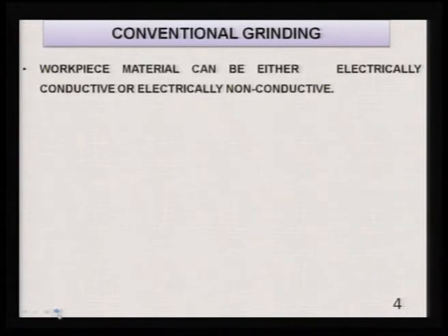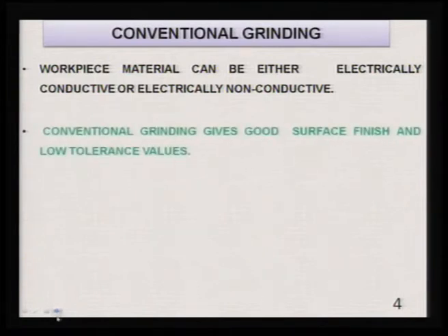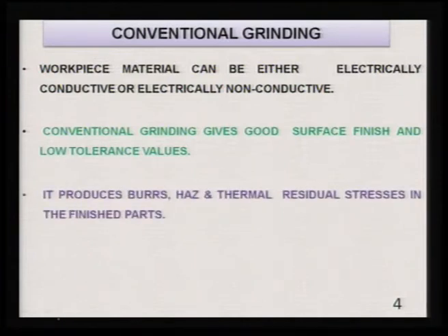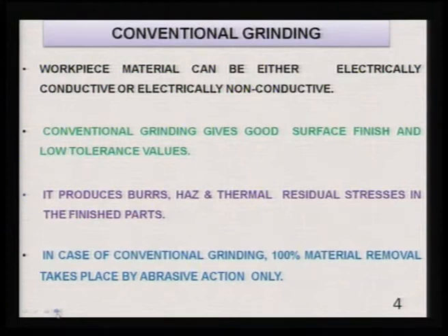In conventional grinding, as we all know, workpiece material can be either electrically conductive or electrically non-conductive. That condition is not required, that the workpiece should be electrically conductive. Conventional grinding gives good surface finish and low tolerance values. It produces burrs, heat affected zone (HAZ) and thermal residual stresses in the finished parts, and definitely the finishing rate is okay. In case of conventional grinding, 100% material removal takes place by abrasive action only.